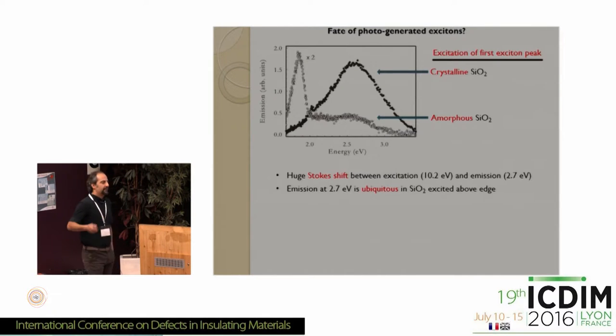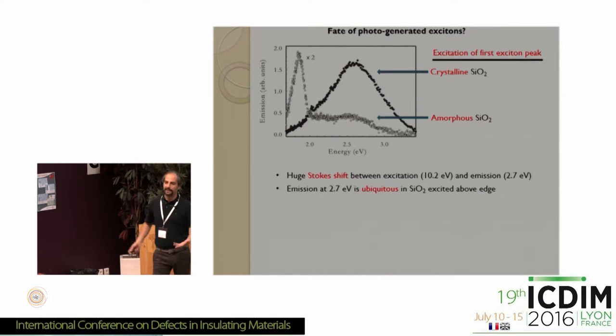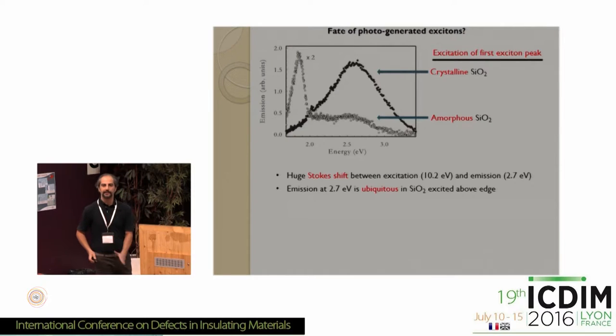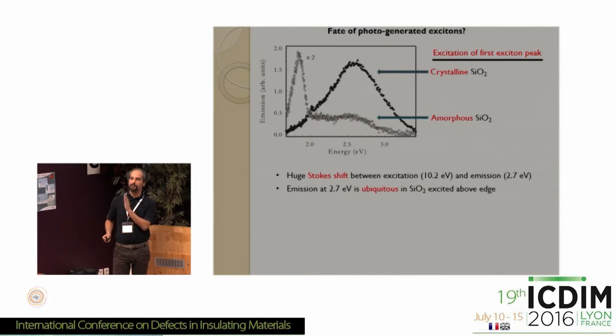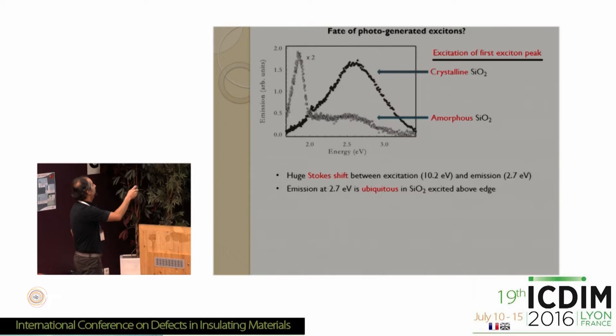Okay, once we know something about the mobility of the excitons, the next step is to know what happens to them after they move. One way of investigating this is to see, for instance, if there is any photoluminescence emitted by the sample when you excite the excitonic peak at 10.2 eV, which is what we did in this experiment. So here you can see the luminescence spectrum of crystalline and amorphous SiO2 as detected when exciting both at 10.2 eV, meaning in the first excitonic peak. There is this band at around 2.7 eV, which is present in both, except it's more intense in crystalline SiO2 and less intense in amorphous SiO2. Then in amorphous SiO2, you have an additional band around 1.9 eV.